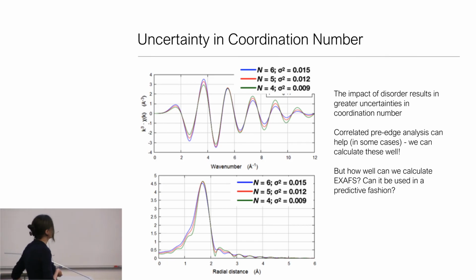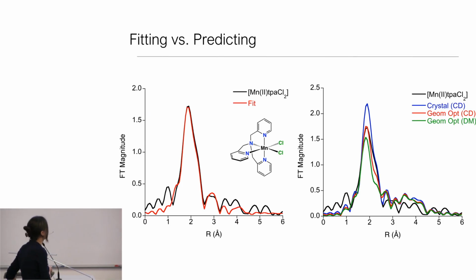And one of the questions we had going into all of this is, to what extent is EXAFS predictive? And here what I want to point out is that we can do a pretty good job of fitting EXAFS, right? This is a small molecule where we have a crystal structure. We put the parameters into FEFF. We group them as I showed you on the previous slide. We fit them against our data, and the red line is the fit. It looks reasonable.